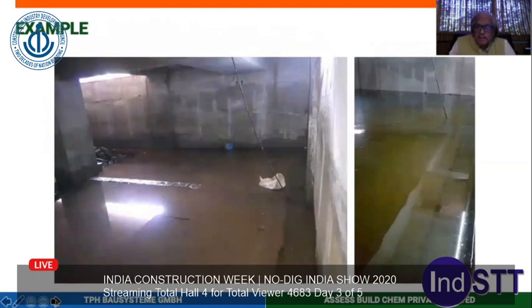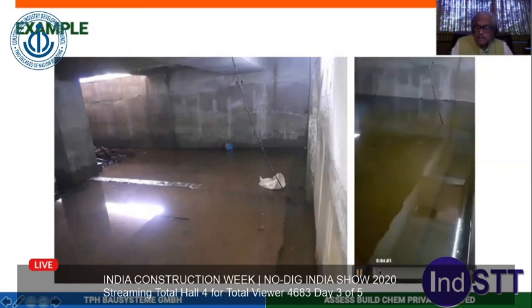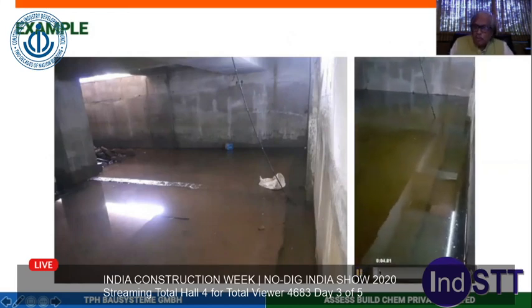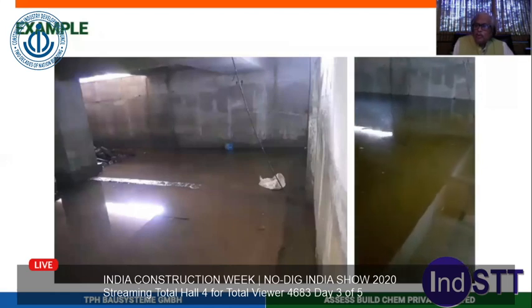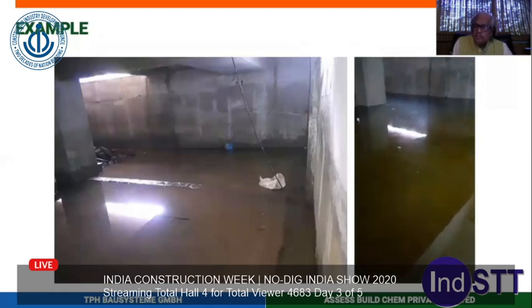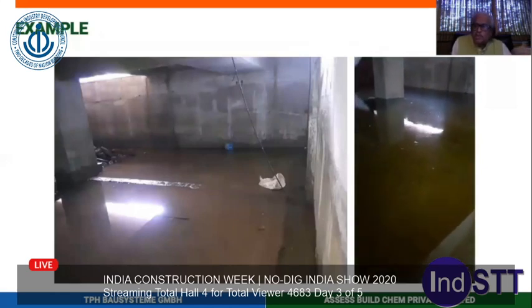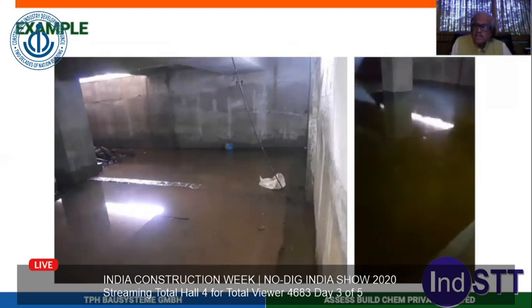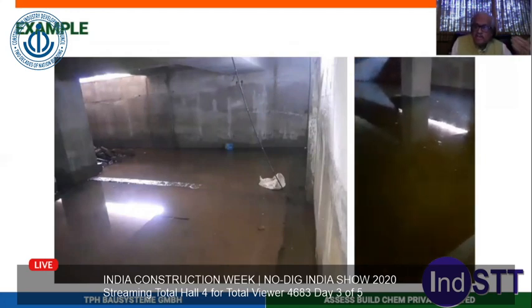This can be similarly used in our basements. We are having a lot of problems in our basements. The water comes inside and you cannot stop it by foam. If you stop it by foam, tomorrow, once the foam is thrown out, the foam is not durable. These materials are tested for durability of 100 years.